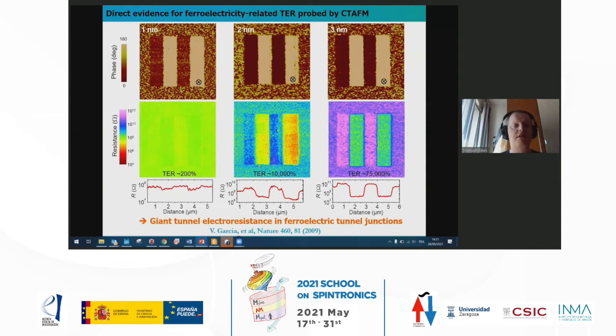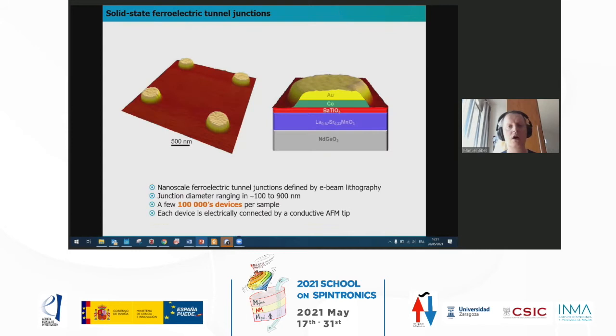And then we use another scanning probe technique, which we have in our lab, which is called conductive AFM microscopy. And we measure the local resistance across these domains. And we found that the resistance was very, very different, depending on whether we were sitting on top of a domain with the polarization pointing up or down. And you see that we have very large contrast, up to 75,000% here. So we confirm this giant tunnel electroresistance in ferroelectric tunnel junctions. And you can see here that the effect increases strongly with the thickness, which is also what you expect from theory.